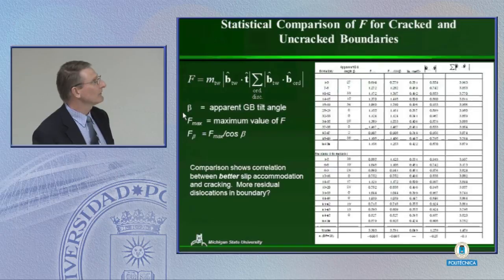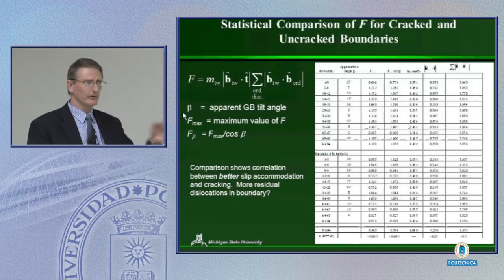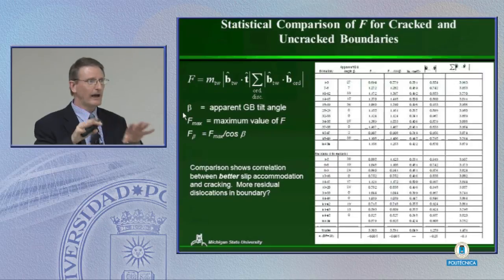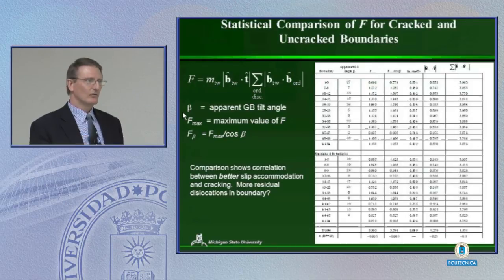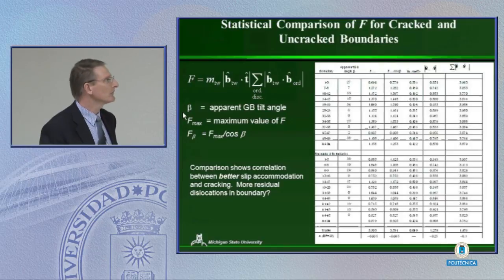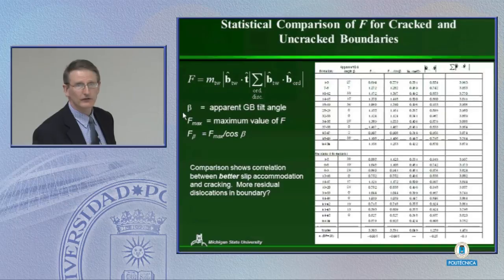And so what we've done here is we've used this factor and we've calculated it for the cracked boundaries and the uncracked boundaries. And we looked at those populations and did a Student's t-test. Are you familiar with the t-test that compares two populations? The question it really asks is, is it actually one population or is it two populations? Based on this factor, we do this t-test and we get the probability that these are actually the same population of 0.005, which suggests that these are actually distinct populations.